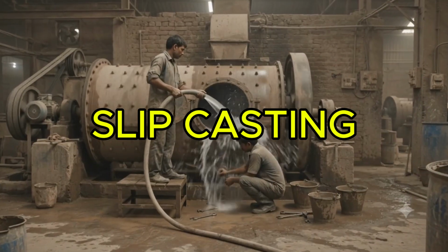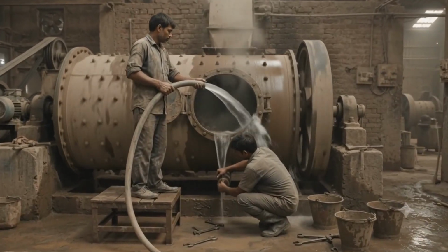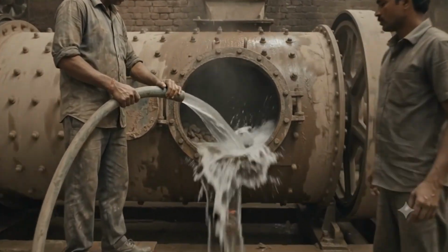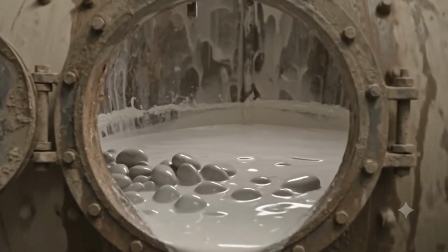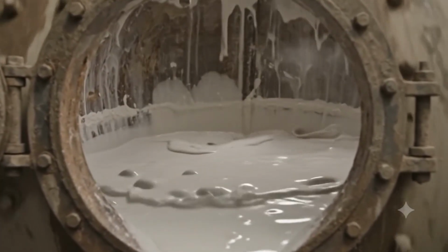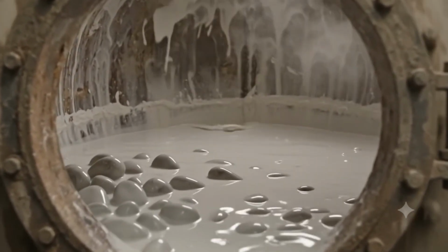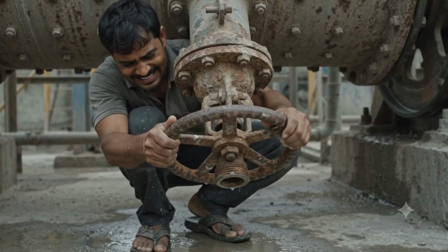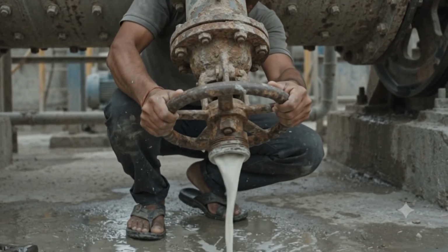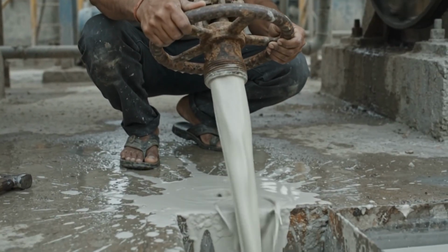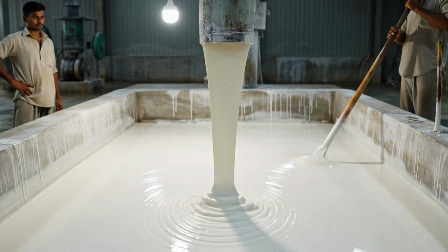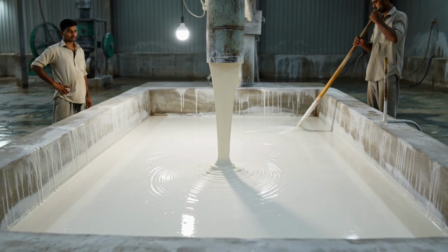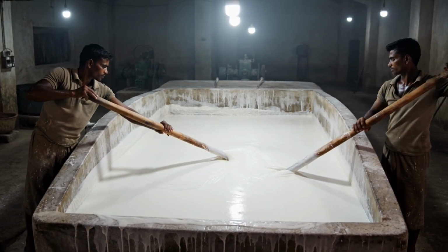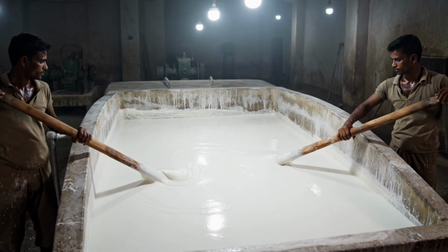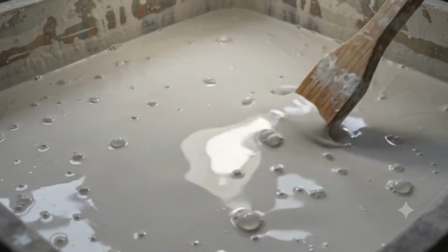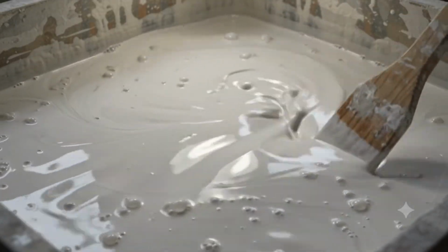Then the lid. After all that grinding, something amazing happens. Workers add water to the ball mill, and the whole mixture transforms into a smooth, creamy liquid called slip. Think of it like a very thick, very smooth clay milkshake. When the mill stops, workers open a large drain valve at the bottom, and this white liquid slip flows out into a big collection tank below. Workers stand by, stirring it constantly with long paddles to keep it from separating. The consistency has to stay perfectly even, not too thick, not too thin. The slip is the lifeblood of the entire process. Everything from here on depends on how good it is.